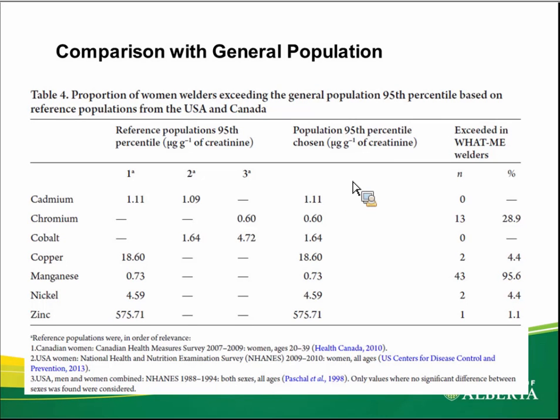So what we did is if we had a Canadian value for women, we used that as our 95th percentile for comparison purposes. If we didn't have a Canadian value, we then tried to use an American value for women. And if we didn't have that, we defaulted to just using an American value that was combined for men and women. And so that's what the 4th column shows here, the population 95th percentile that we chose. So to be very clear, we did choose this, and then we compared the proportion of the women in our sample that exceeded the 95th percentile.